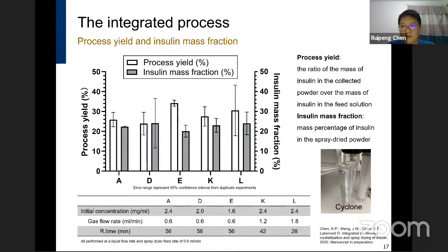If you look at this figure, there's no substantial difference in both process yield and insulin mass fraction for all the tested conditions. The process yield is in the range of 20 to around 34%, which is low compared to the recovery of the standalone crystallization. We think this is because of the loss of particles in the cyclone of the spray dryer, because this spray dryer is not intended for collecting small particles in this size range. This can be further improved if we modify the cyclone or optimize the spray drying conditions. For the insulin mass fraction, it is slightly over 20%. This also confirmed there's a large amount of other compounds in the spray dried powder.